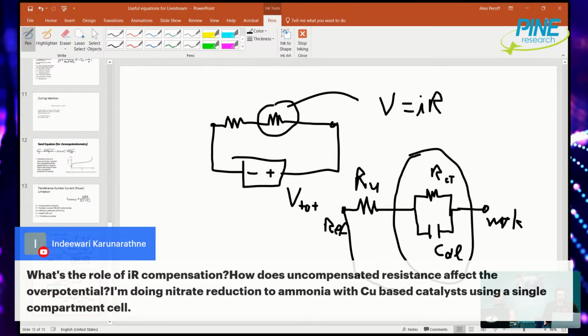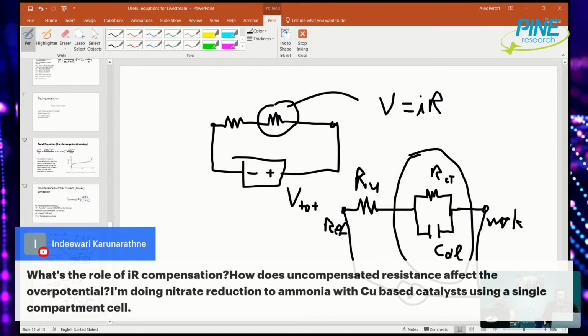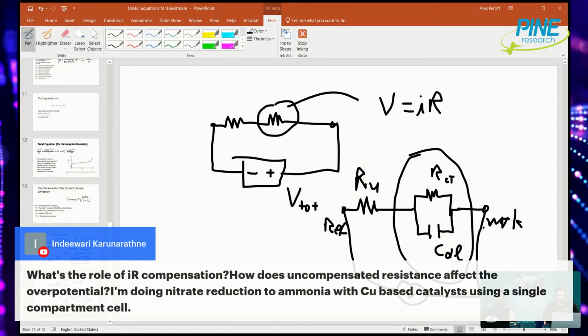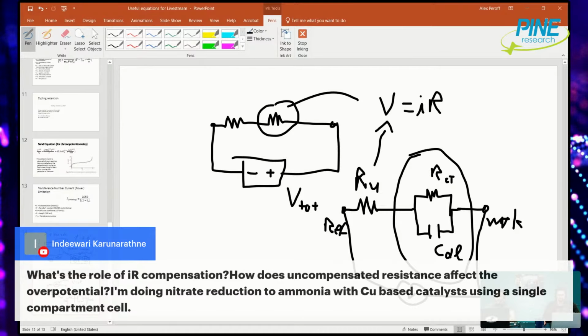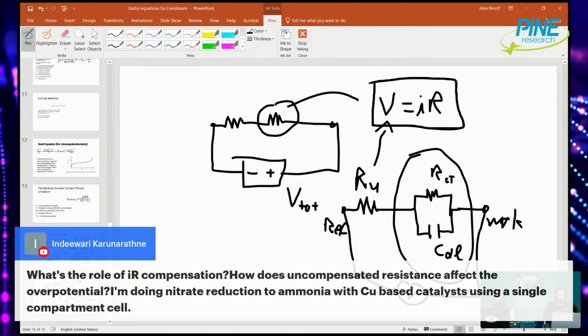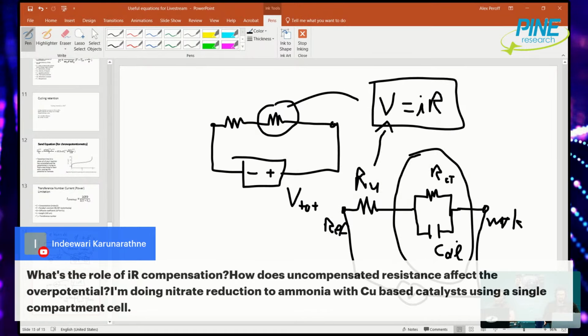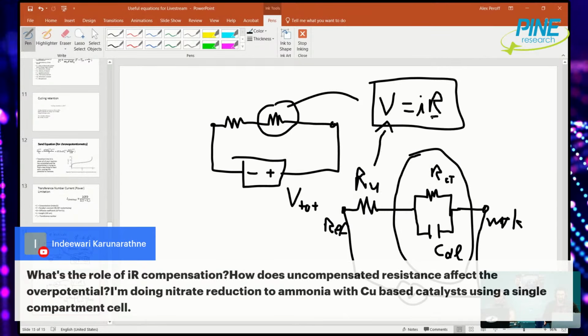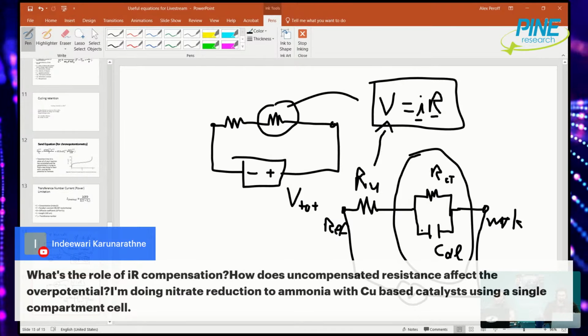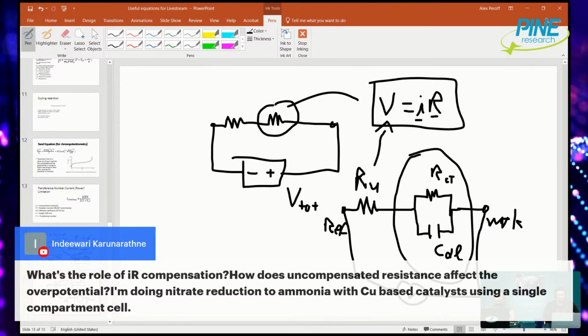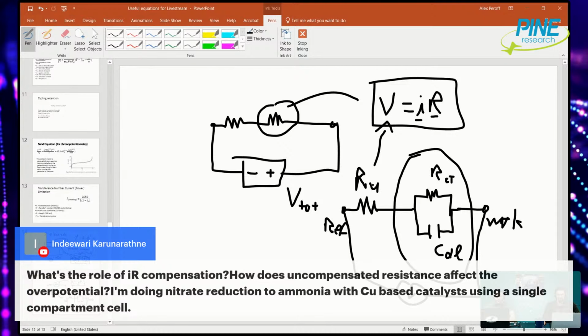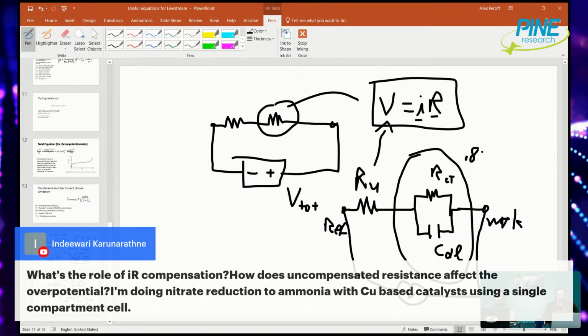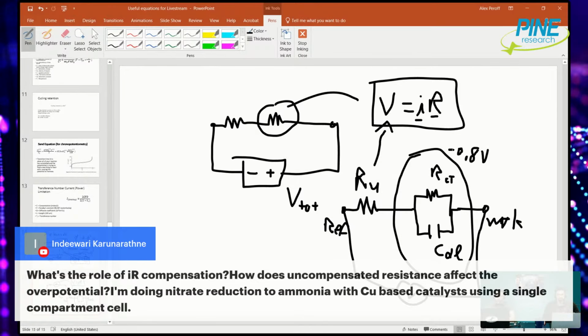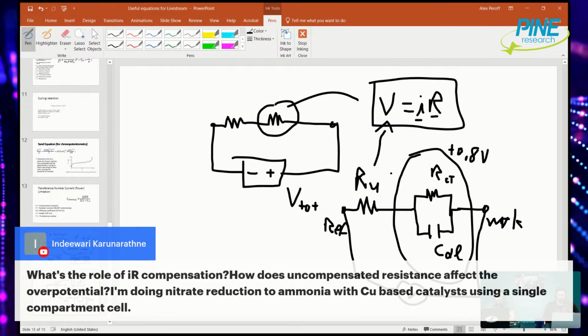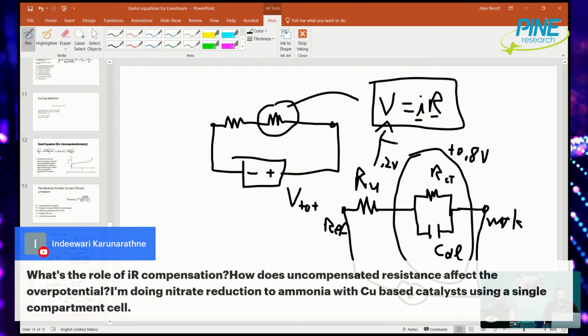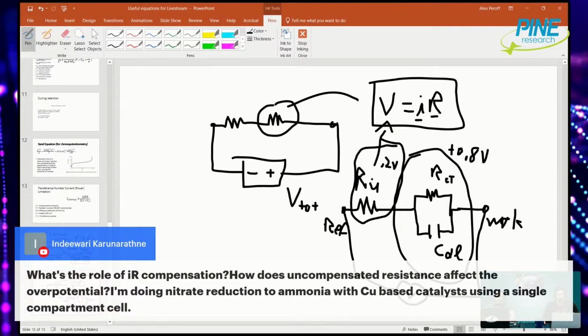So when you tell your potentiostat, hey, apply +1 volt from the working to the reference electrode, a fraction of the applied voltage is consumed in this solution resistance. That fraction of the voltage is equal to the resistance times the current. So you tell your potentiostat to apply +1 volt between the working and the reference electrode, but in reality you end up applying something like 0.8 volts. That's what you actually applied to this system, because 0.2 volts, I'm just making up some of the numbers, of course, was consumed in this IR, in the solution resistance.